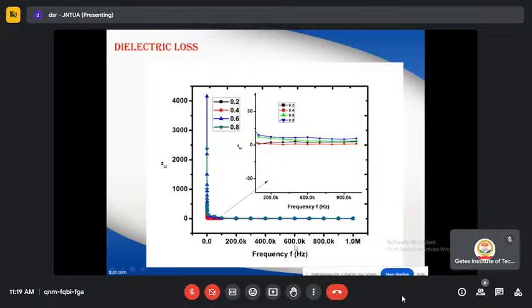The present samples showed high magnitude of epsilon dash and epsilon double dash at lower frequencies. Also, the space charges become more dominant at a small frequency. As a result, a large amount of polarization will be induced, leading to high epsilon dash and epsilon double dash. When we move towards high frequencies, the epsilon dash along with epsilon double dash were reduced and remain almost constant. The reason for this may be the lagging of space charge carriers behind the applied electric field with the increase in frequency.